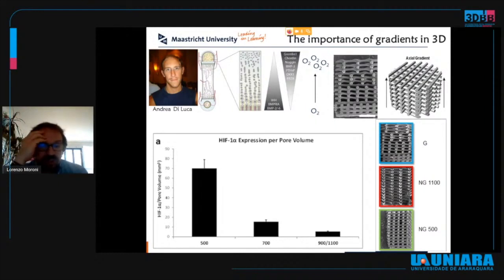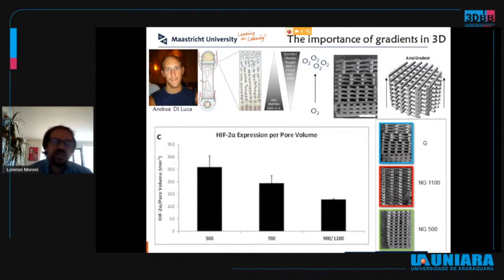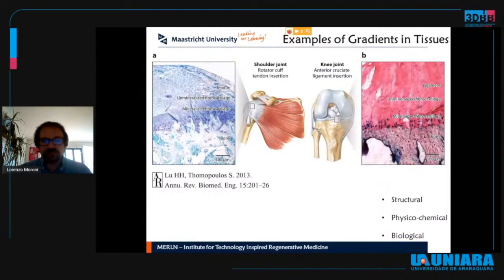And indeed, we saw that both in the expression of HIF-1 alpha as well as HIF-2 alpha, the protein was much higher present in the lowest pore size compared to the other pore size of the gradient scaffolds. So again, further confirming this relation between predisposition of cells into differentiating towards the osteochondral tissue versus the possible level of hypoxia in these pores, and therefore the possible local level of oxygen concentration.